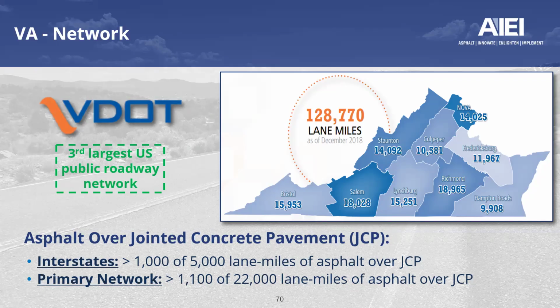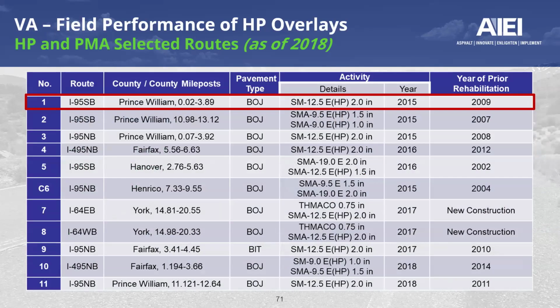So when Virginia DOT wanted to approach the use of HP technology, their primary concern was, first of all, to increase the cracking resistance of the mix being laid down on top of the jointed concrete pavement, as well as mitigate reflective cracking and try to delay and resist that distress as long as it could. The first project was in 2014, in a rural area. It was a subdivision, just for trial purposes. In most cases, the use of HP was intended to mitigate cracking in general, reflective cracking in particular.